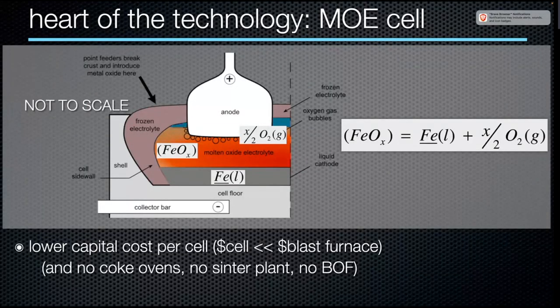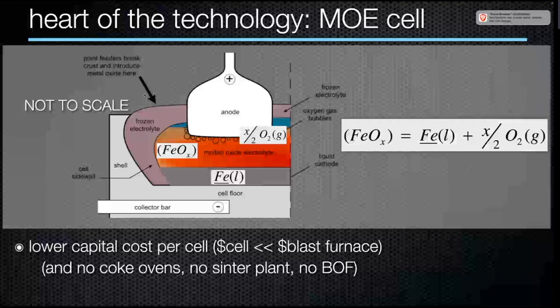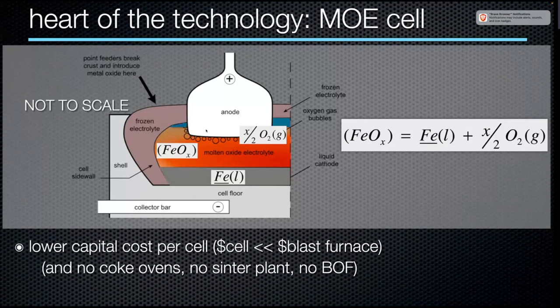See, here in the molten oxide electrolysis, I don't care if I have big chunks of iron oxide, if I have fine particles, everything is going to dissolve in the electrolyte. But in the blast furnace, you have to sinter into pellets of a certain size and a certain porosity. Otherwise, if they're too dense, then by the time the sinter reaches the bottom of the blast furnace shaft, it will not have been fully converted.